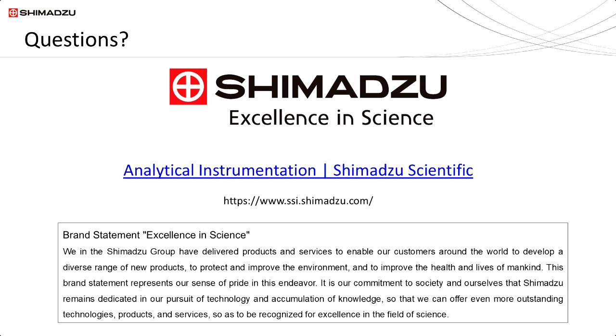Another question for Keith. What are some of the differences between high sensitivity and normal sensitivity catalysts, and how do they achieve different detection limits? That's a great question. So the active ingredient in both catalysts is platinum, with the regular catalyst being platinum-coated alumina beads, and the high sensitivity catalyst being platinum-coated wool. So the platinum-coated wool offers lower detection limits because you can actually inject more sample onto that catalyst. It has more active surface area.